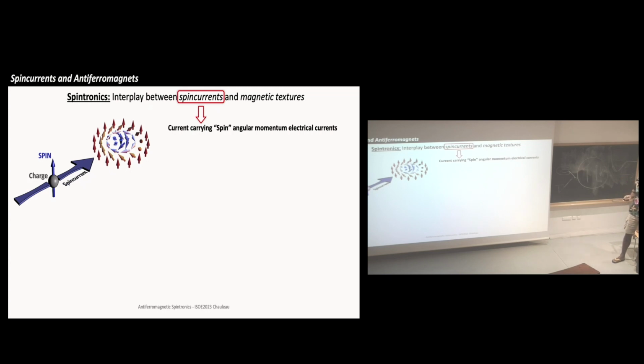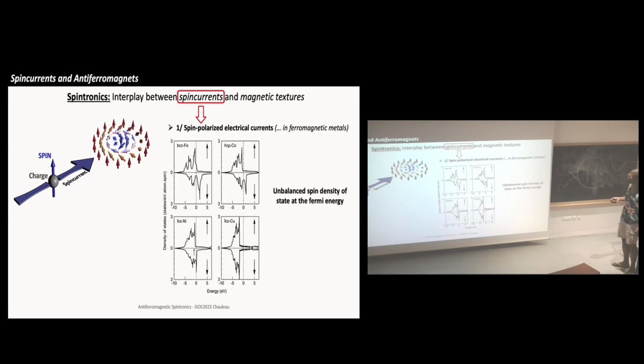And the first thing which has been shown is spin polarized current. Michel already introduced this to you, but I'll do a quick reminder. Especially in ferromagnetic metals, since you have an imbalance of spin up and spin down, if you drive a current, then your current will typically be spin polarized. So for example, in copper, which is not ferromagnetic, the current is not spin polarized. But if you look in cobalt, iron, or nickel, then at the Fermi energy there is this imbalance. So this is typically what we call spin polarized electrical current. That was the first one they worked with.